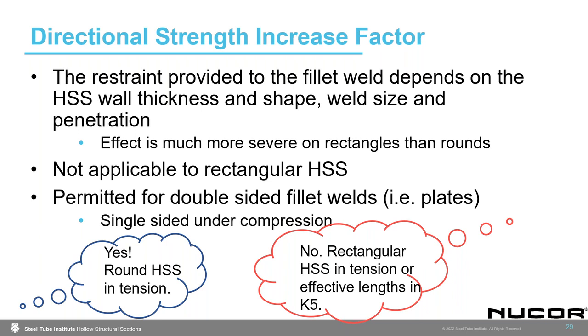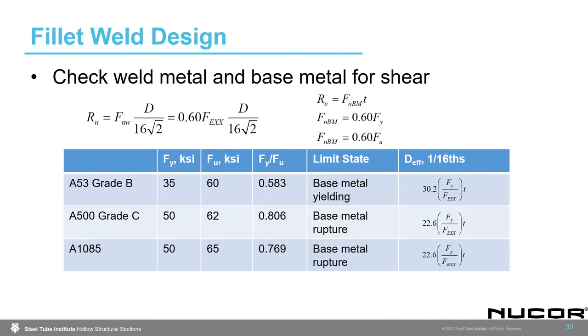In the previous specification, it was implied. In the upcoming specification, it's very clear cut that the 1.5 increase cannot be applied to rectangular HSS that are in tension. It can be applied to round HSS that are in tension. It can be applied for double-sided fillet welds, like if I'm welding a plate to an HSS, whether it's round or rectangular, as long as I'm welding it on both sides, like in a single plate connection, then it can be used if in tension. And obviously it cannot be used for the effective lengths that are given in K5. So a little bit of clarification on when and where you can use that 1.5 strength increase.